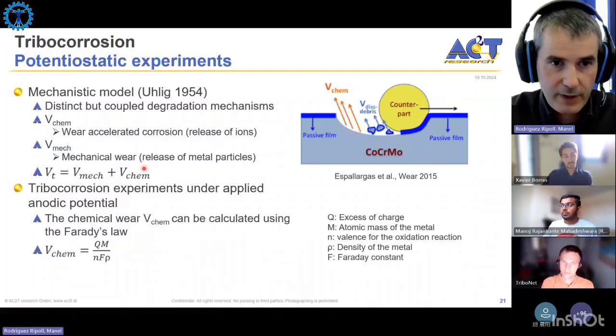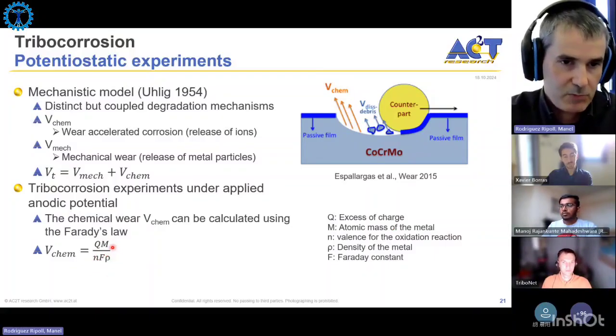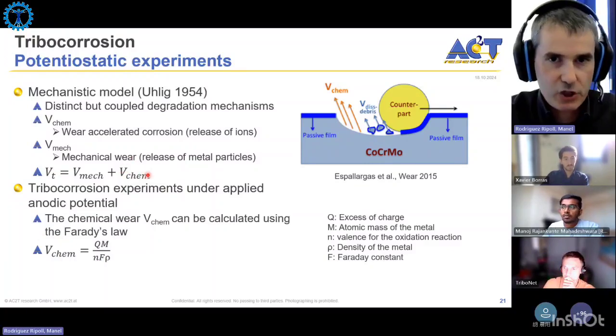The chemical wear, we can calculate it using the Faraday equation. So we have the charge, which is the integral of the current that we measure with the potentiostat. We have the atomic mass of the metal, we have the valence of the metal, we have the density. So these are constants that we can check in books that are well known for the metal that we have. And the Faraday constant is also well known, so we can calculate the chemical wear. And when we know the chemical wear, because it's calculated based on the potentiostatic data, and the total volume is calculated using profilometry, then the difference between both of them gives us the pure mechanical wear occurring due to the formation of wear debris.